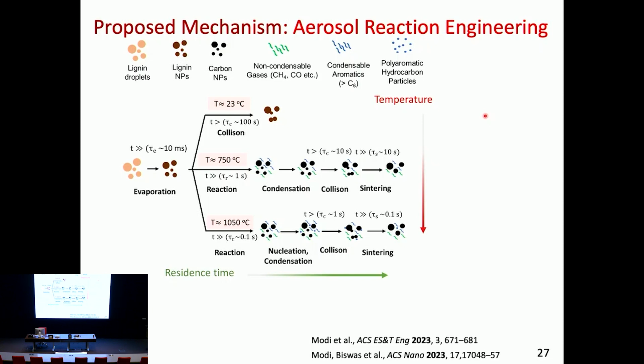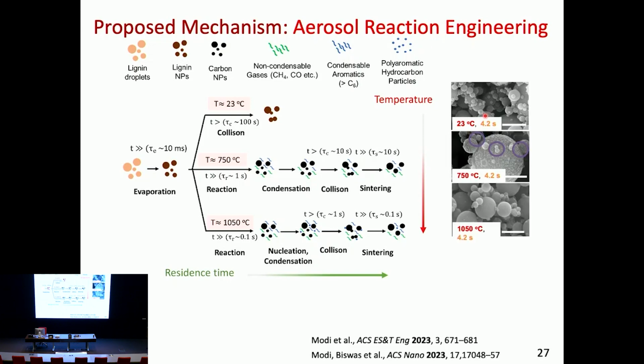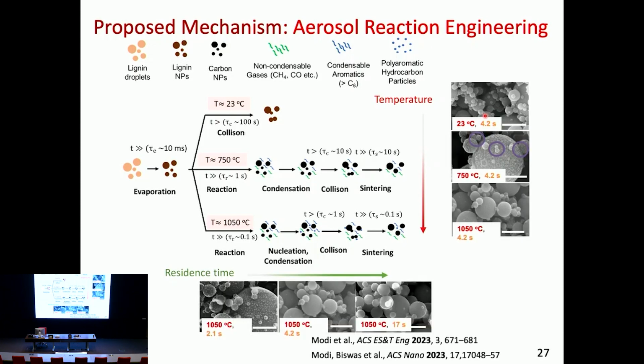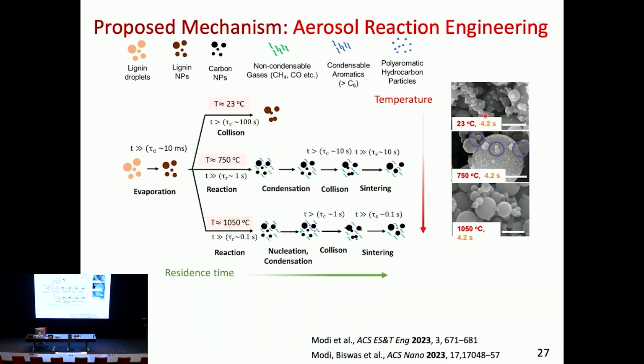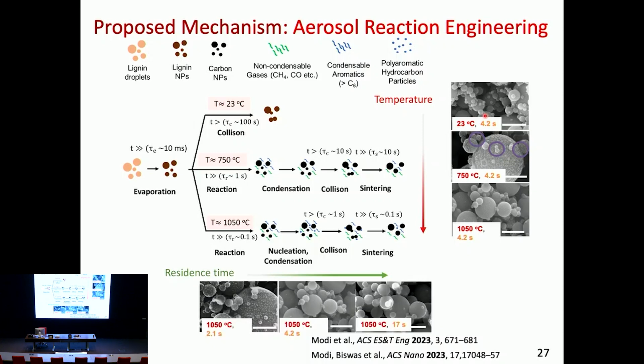If I start elevating the temperature, I begin to now promote chemical reaction, start breaking up these polymeric chains, and I can have then downstream condensation, collision, sintering, and so forth. I'm throwing sintering in because many of the practical reactors have big challenges with sintering taking place with these agglomerates and plugging up, right? And then of course I could go even higher and end up with carbonaceous particles. You can collect these particles, and they all of course look pretty, but they have subtle differences in the electron micrographs, also in addition to things like the surface area and so forth.